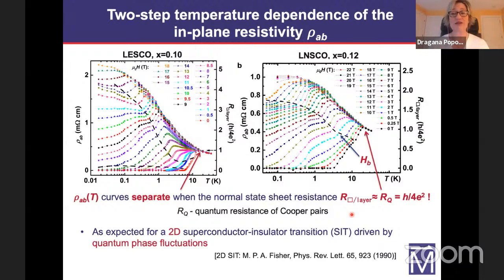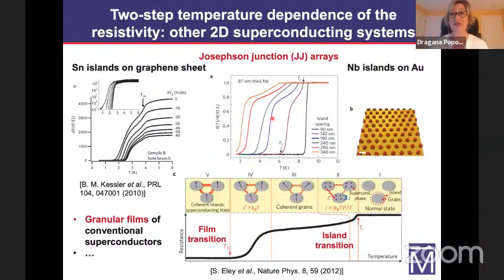fluctuations. There is another similarity to other 2D superconducting systems that I would like to emphasize at this point, and this is the existence of this two-step transition. This is something that is actually very well known in various granular films of conventional superconductors. It has also been seen in relatively clean heavy fermion and iron-based superconductors with competing orders, but I think it is best understood based on these Josephson junction arrays that have been engineered by depositing islands of conventional superconductors such as niobium or tin on various substrates such as gold or graphene.